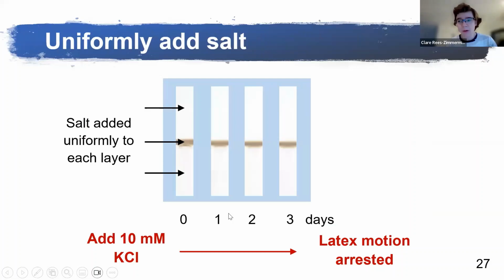Now, I wanted to confirm what type of diffusiophoresis was happening. Therefore, I added salt uniformly to each layer, so a kind of background salt concentration. Here I added 10 millimolar of KCl. That's because the background salt should shield the electric field, and it should affect our process if it's electrolyte driven. And indeed, you see that the upwards latex motion is arrested when we add our background salt. So it's supportive of it being an electrolyte driven process.